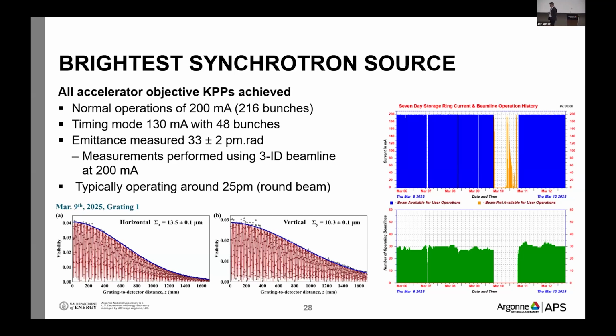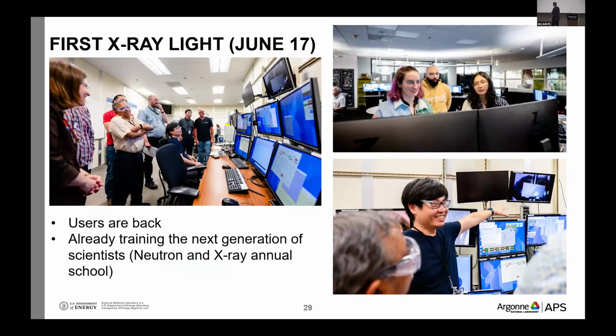The success of this has also been greatly impacted by the fact that the installation was so precise. I forgot the exact RMS of installation, but it's about a few tenths of microns, girder to girder and magnet to magnet around the ring, which is certainly impressive. And also very good vacuum to start with. So then we got first light, I described that, June 17.